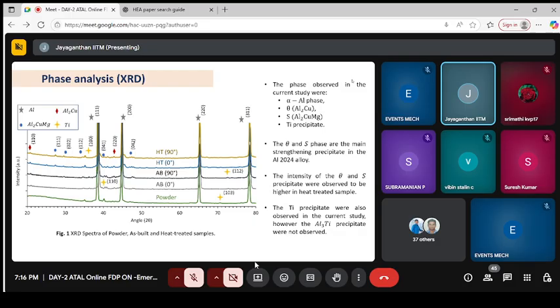And then having alloying elements like copper and magnesium, we end up getting a unique peak for the presence of precipitate, that is Al2Cu precipitate, that we call theta, which has a particular crystal structure. That's where we use the theta symbol for Al2Cu. And having copper and magnesium along with aluminum, we see the formation of precipitate Al2CuMg. That phase is called S phase, plus titanium precipitate also.